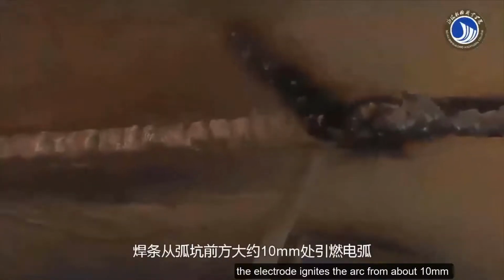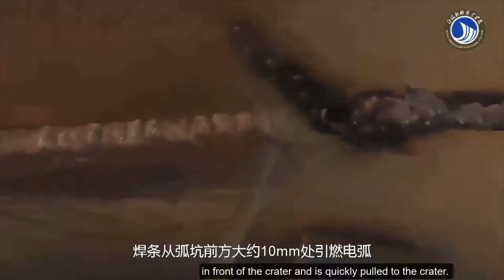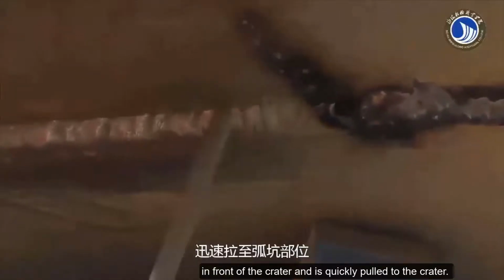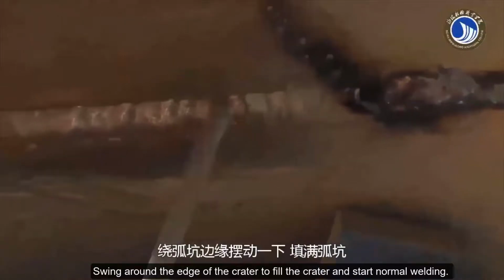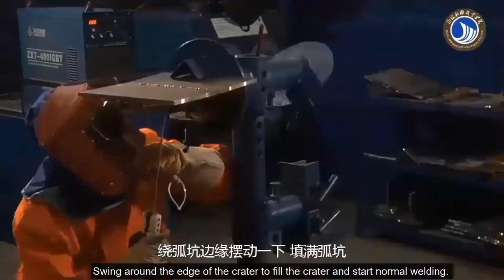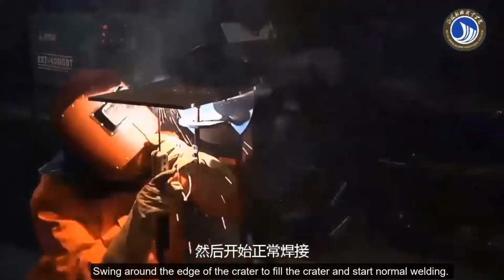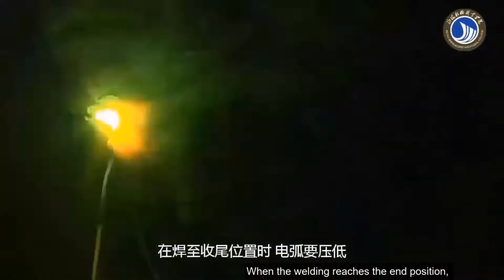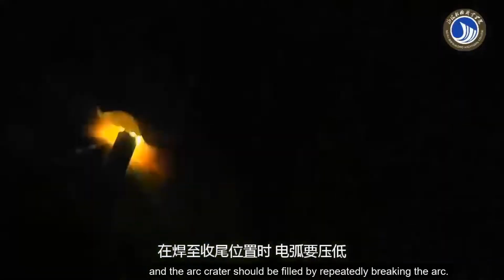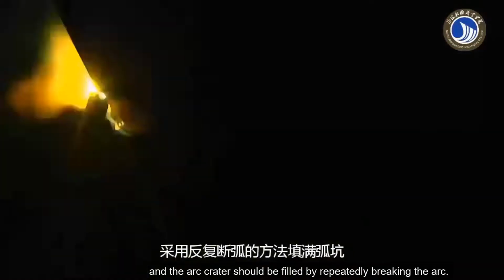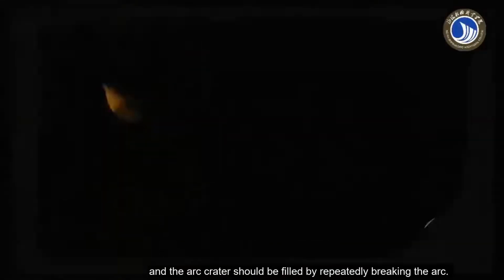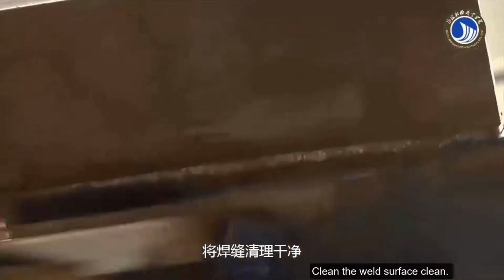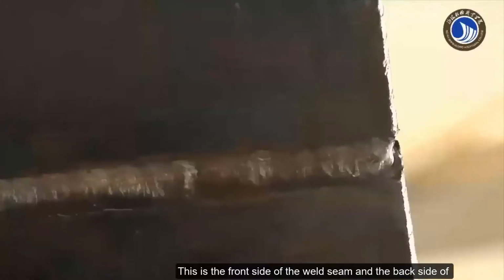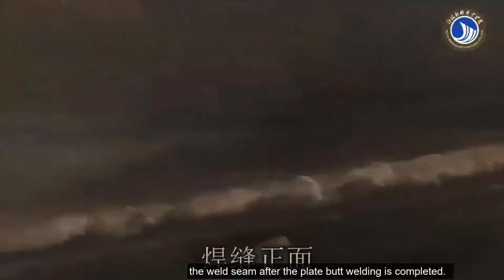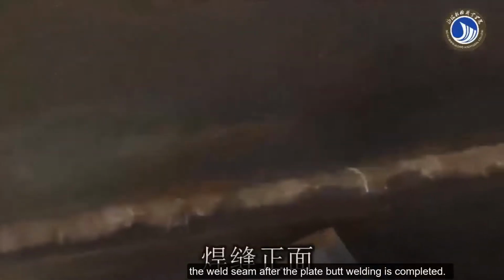During the joint operation, the electrode ignites the arc from about 10 mm in front of the crater and is quickly pulled to the crater. Swing around the edge of the crater to fill it and start normal welding. When the welding reaches the end position, the arc should be lowered, and the arc crater should be filled by repeatedly breaking the arc. Clean the weld surface. This is the front side and the back side of the weld seam after the plate butt welding is completed.